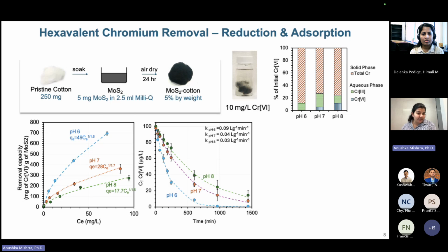We also saw that the kinetics at different pHs is different. So the neutral pH conditions actually have slower kinetics of chromium removal versus the lower pH kinetics.